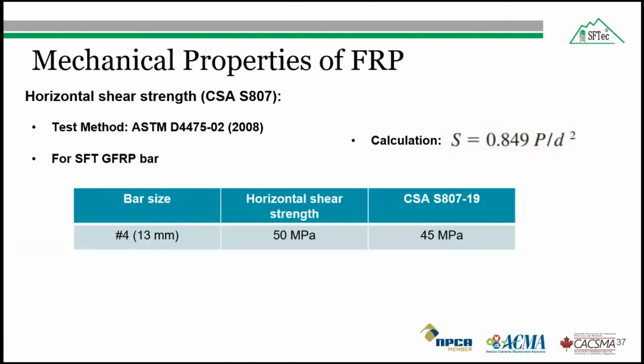So the horizontal or interlaminar shear strength was calculated according to this equation, and this is an empirical equation based on the number of tests. Where S is the horizontal shear strength in megapascal, P is the breaking load in Newton, and D is the diameter of the FRP bar in millimeter.